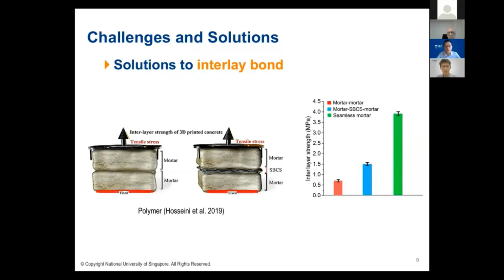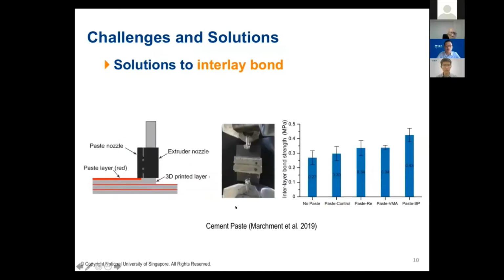Next, I'm going to talk about the solution. Oh, sorry, one research group in Melbourne, Swinburne University, they are trying to use cement paste to increase the interlayer strength, because cement paste is relatively cheaper and more affordable than polymers. So they investigate different mix proportions of paste. So their tensile strength is tested in this way. They directly pull the samples and see how strong the tensile strength is. And a very good result has been obtained from this research group.